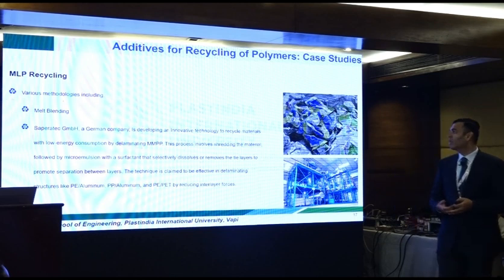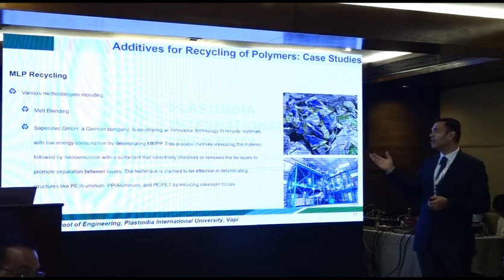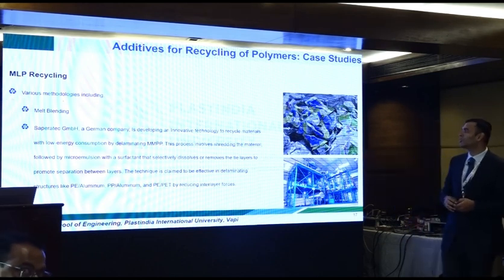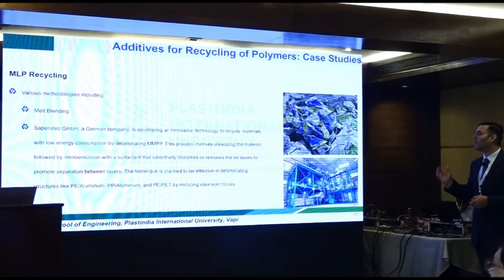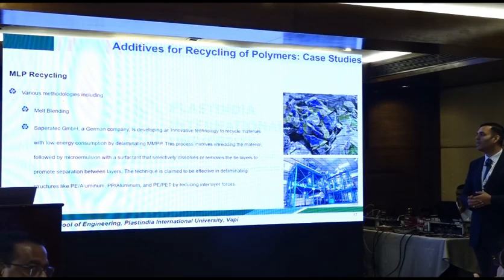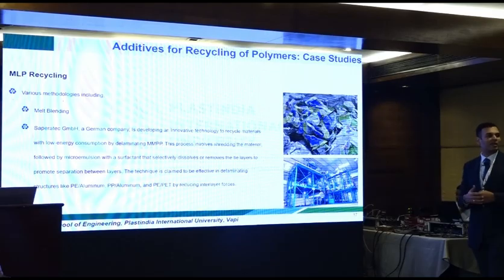on multi-layer. So there are certain companies, there is Saperatec GmbH, it's a German company, it is developing an innovative technology to recycle materials with low energy consumption by delaminating these multiple layers. Once they get delaminated, you can process them on an individual basis. This process involves shredding the material followed by creating a micro emulsion with a surfactant. So when you are creating a micro emulsion with a surfactant, you will have then selective ability of the material to go in one phase and to go in the other.